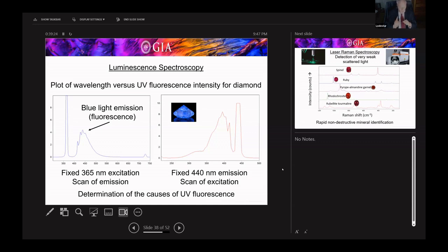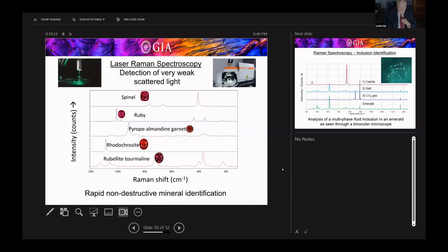But you can also switch this around. You can also, in this case, fix the emission, which here is going to be at 440 nanometers, the high point of the fluorescence. And you can scan the excitation. And you can see exactly what wavelengths in the UV range are exciting that fluorescence. So this allows us to better understand fluorescence in all types of gem materials by this method.